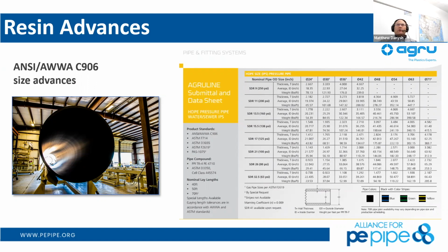Right. So this was an older chart that we've done back to go up to 71 inch. Now we're going up to 10.5 feet in diameter. So yeah, it adds on to this, and we can produce pipe in these SDRs. As you get to be the larger sizes, though, our SDR availability comes down. So once we get out to the very large size, we're only able to do that to an SDR 26 for the 80 PSI. And we also can do striping materials up to a 63 inch. And then after that, it's just black pipe.